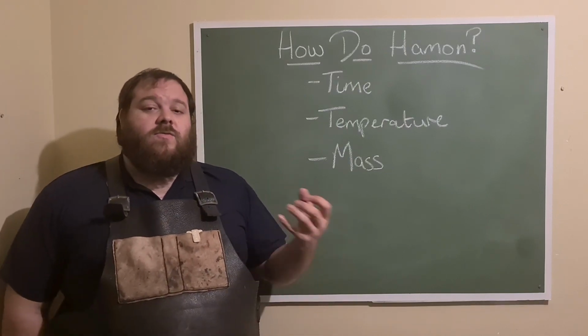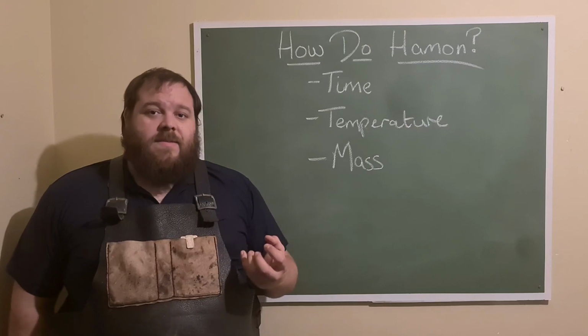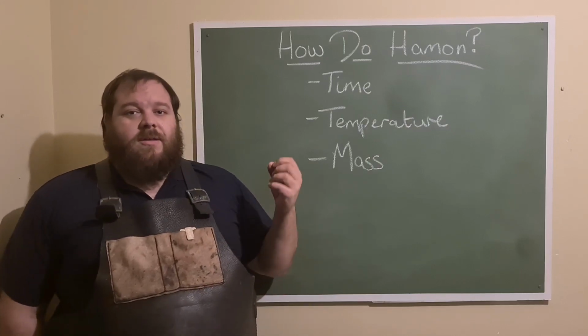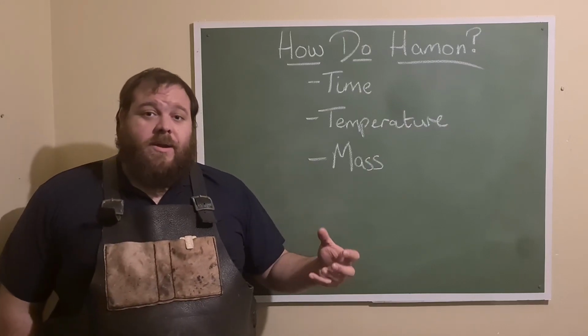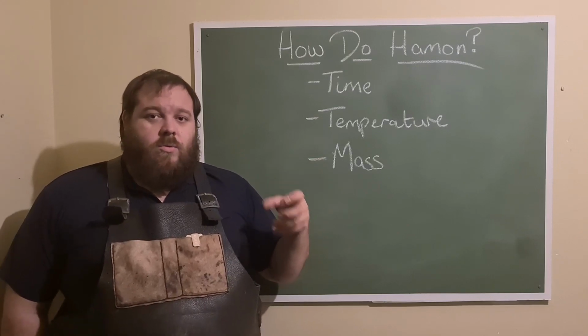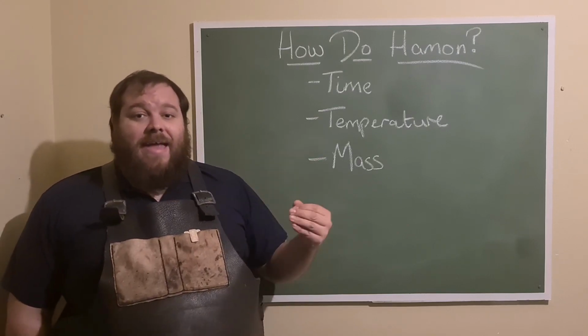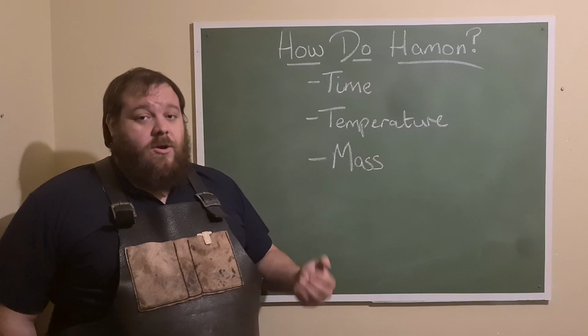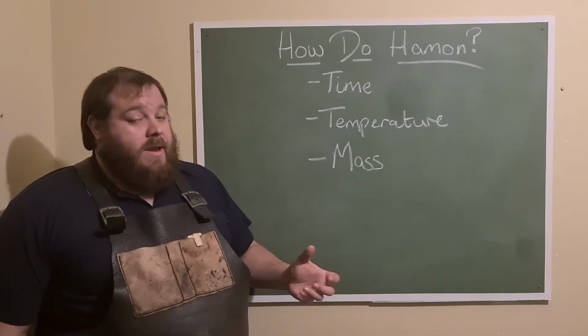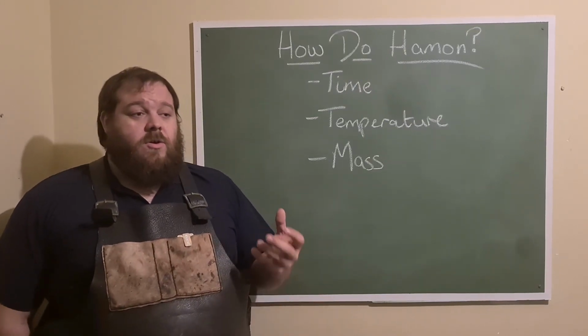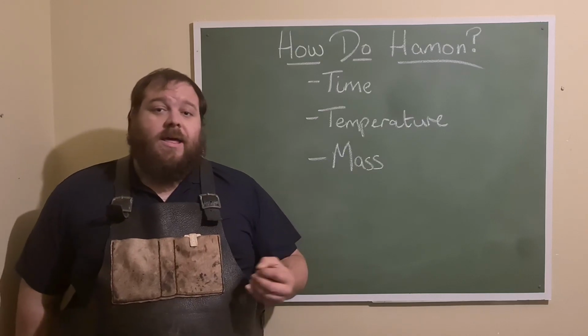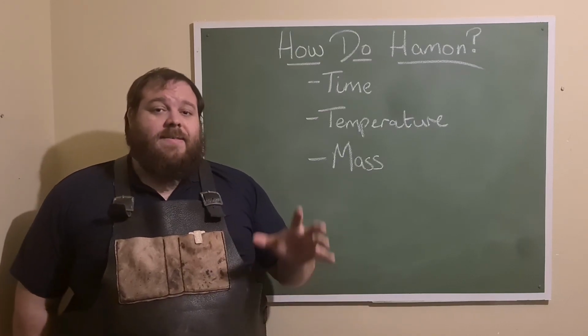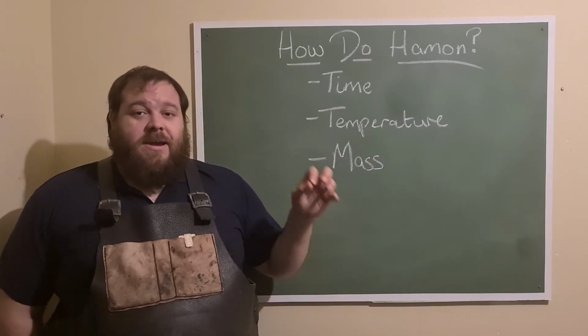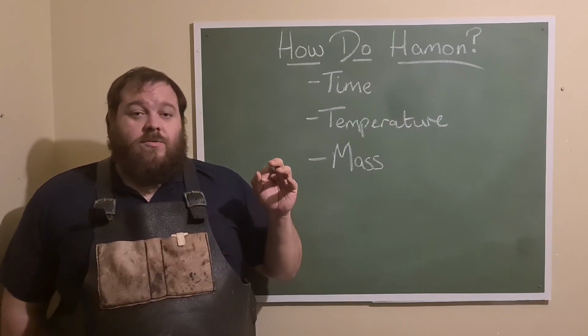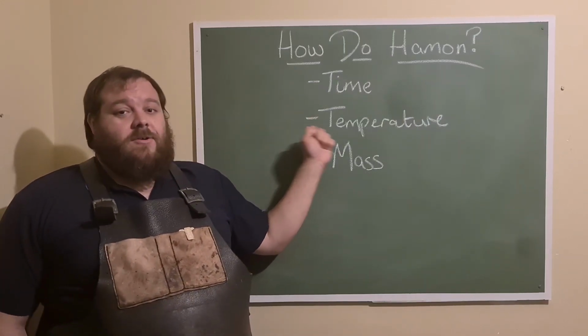What it is doing is retaining heat in the spine long enough that the edge cools really quickly and the spine doesn't cool as quickly. What it's doing is just adding thermal mass. And the reason we know this is because you can create auto Hamon, right? So you can create Hamon without using clay, without using any form of other mass increasing object. All you need to do is use time and temperature to create Hamon.